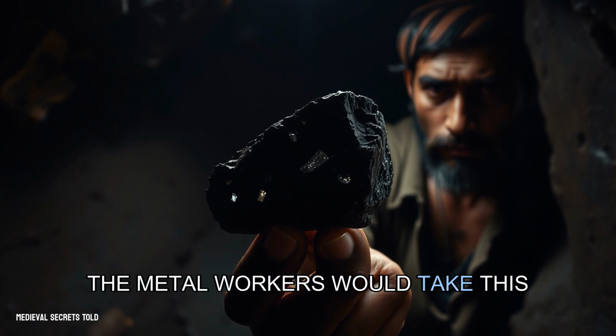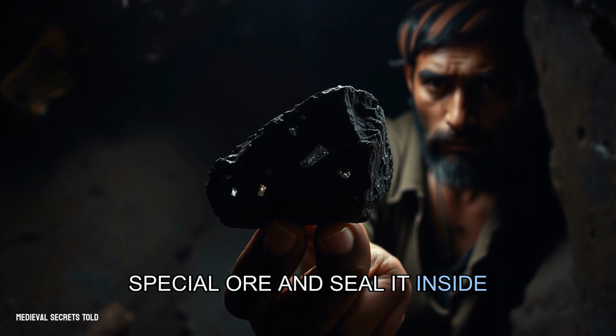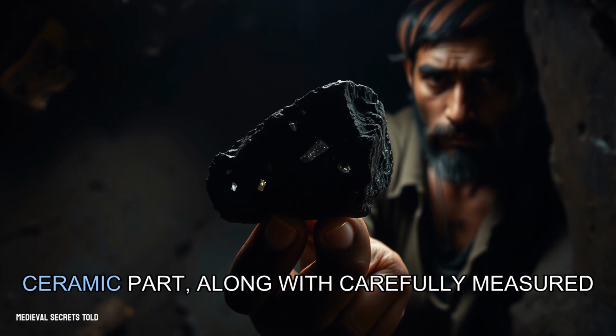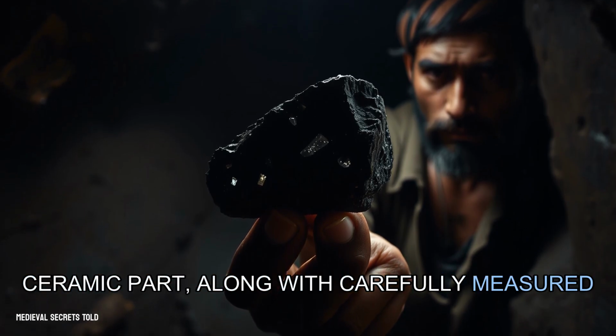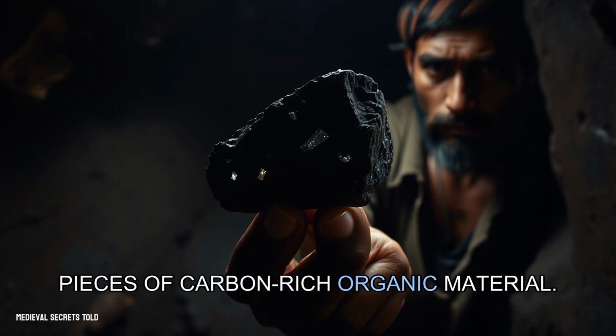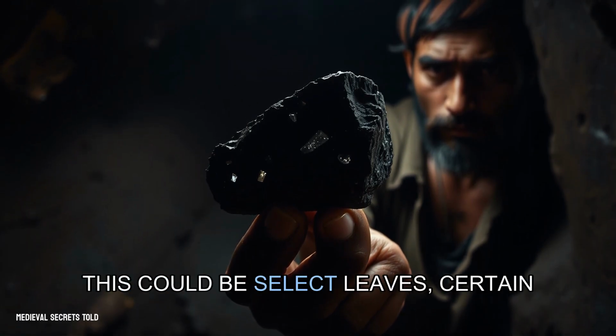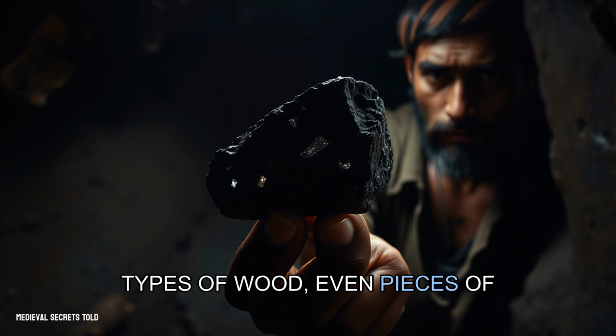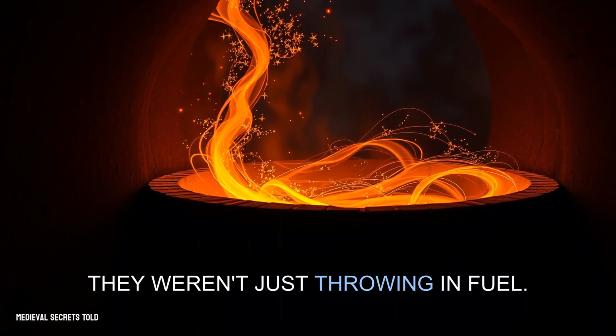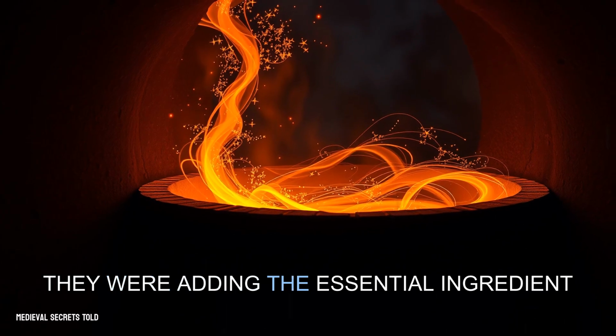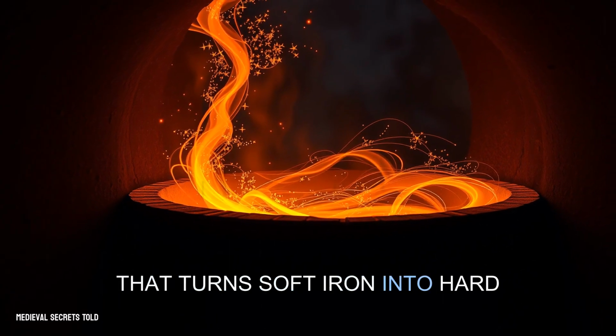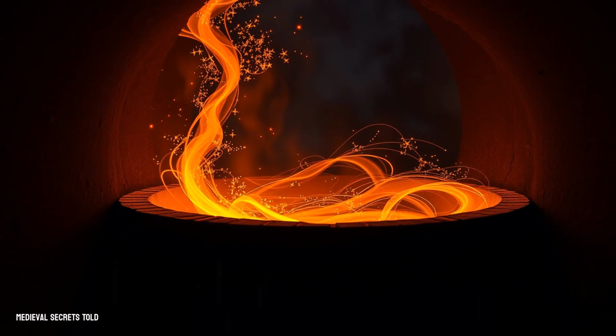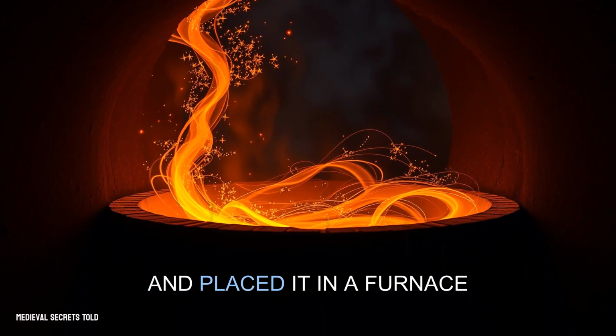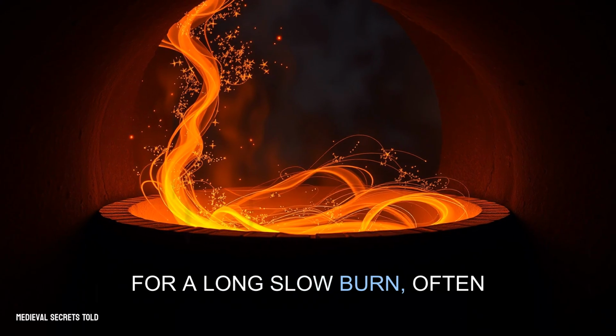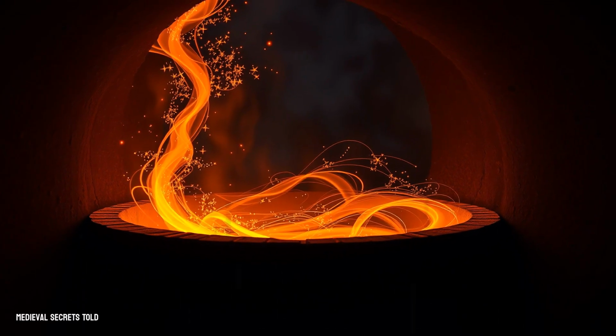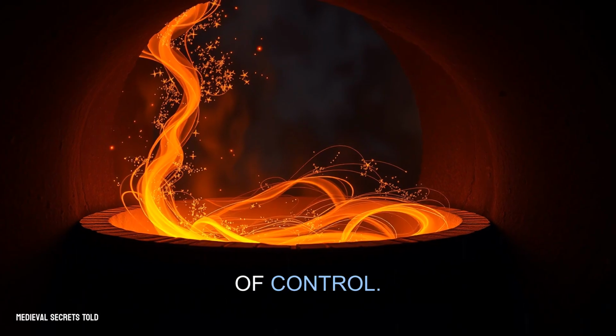The metalworkers would take this special ore and seal it inside a clay crucible, a kind of ceramic pot, along with carefully measured pieces of carbon-rich organic material. This could be select leaves, certain types of wood, even pieces of bark. They weren't just throwing in fuel, they were adding the essential ingredient that turns soft iron into hard steel, carbon. Then they sealed the pot shut and placed it in a furnace for a long, slow burn, often lasting several days. This was the first critical act of control.